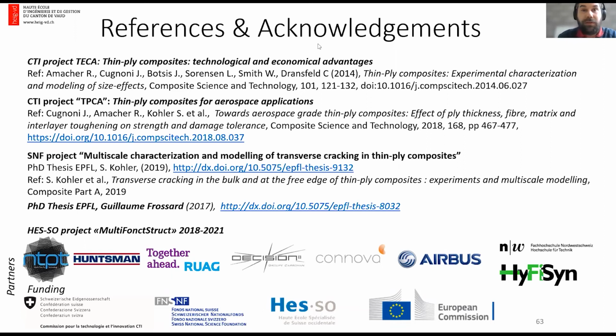The first reason is volume of production. It means that you have to use a pre-preg line for a much longer time to produce 1 ton of material. So this leads to a cost that you cannot really reduce too much, and there are also the consumables used in the production that start costing more than the fibers used, because you have backing papers and films that are costing quite a lot of money as well. So I think thin plies have to be used where they actually bring the benefit. For example, for a UAV or a satellite, 1 kilogram saved is a huge deal.